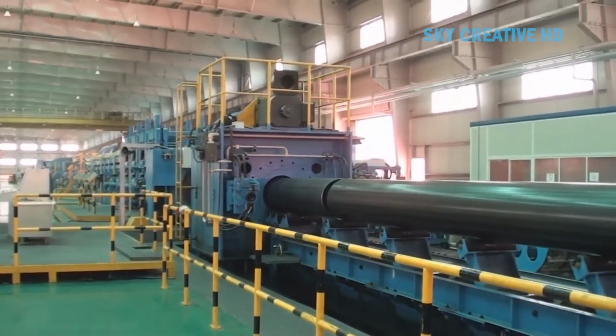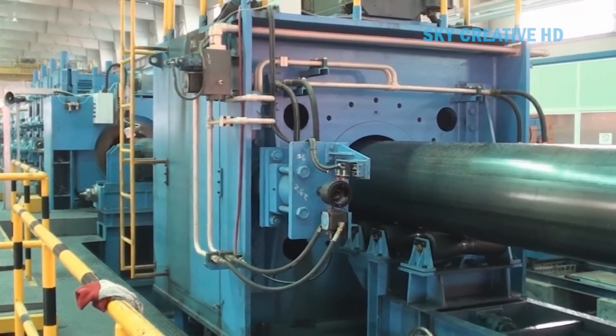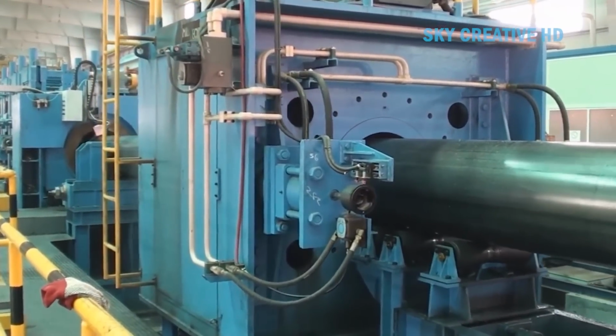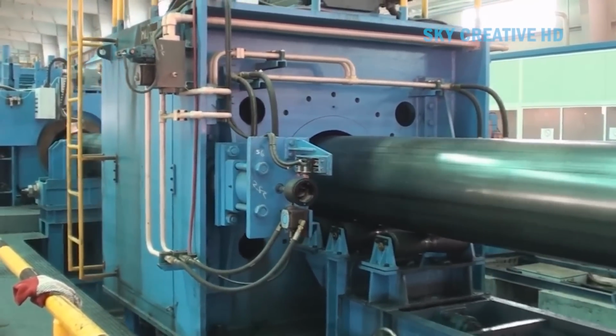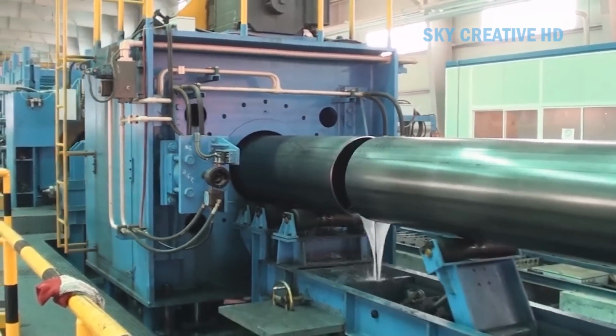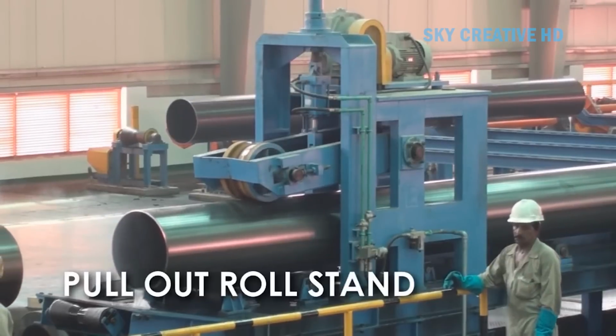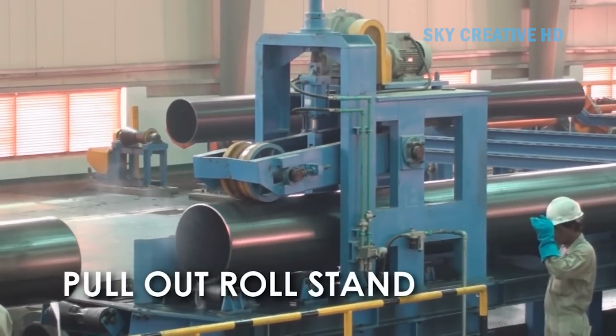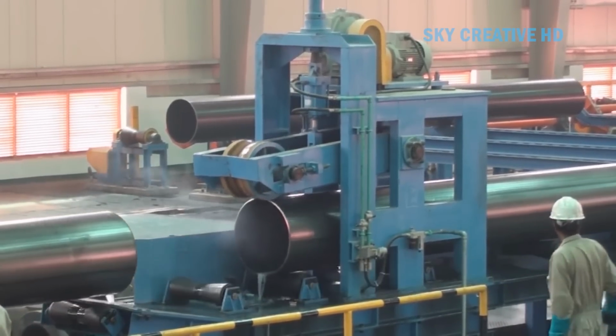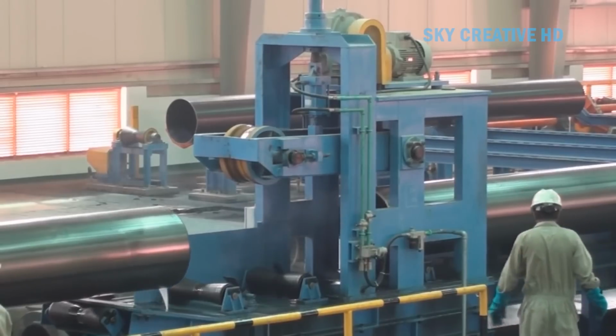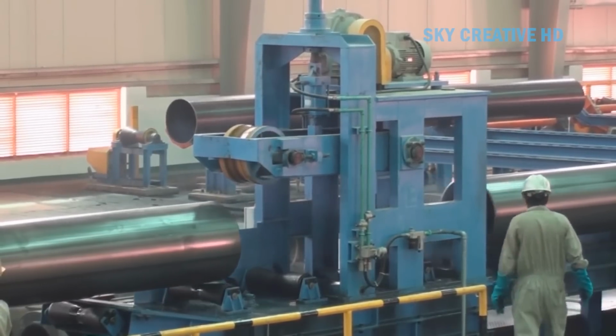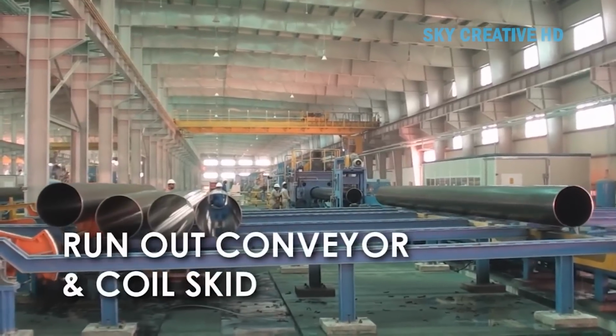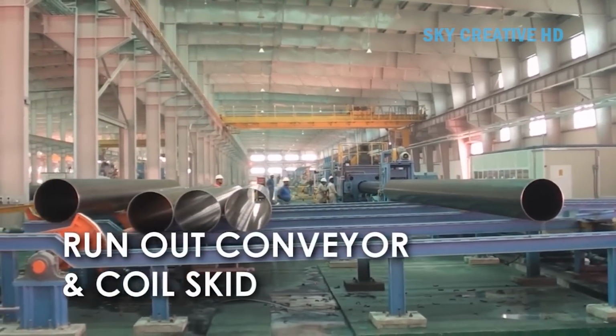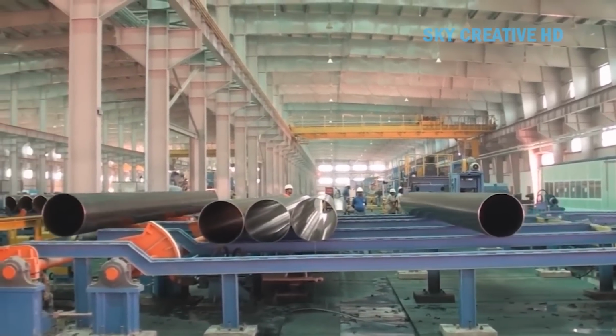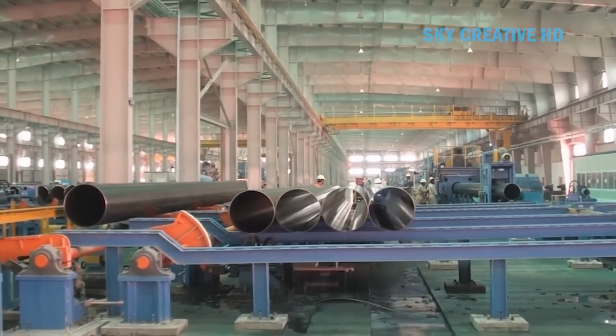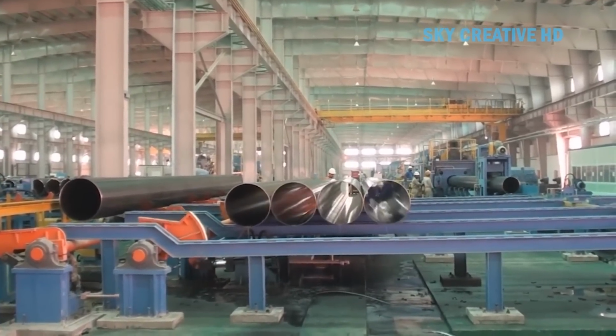The steel edges, after being shaped, are passed through the high-frequency welding system. The temperature control system ensures a uniform weld without voids or cracks, increasing the mechanical strength of the pipe. The pipe is cooled by water or air, stabilizing the size and structure of the material. The final shaping roller ensures the specifications of the diameter, angle, and flatness of the product. The pipe is cut to the required length by the automatic cutting system without deforming the product.